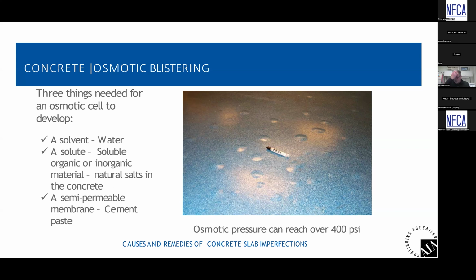And then what's done is it's reprofiled with a cementitious material that is suitable to be indefinitely damp. So you use a different cementitious material over the surface. It does not have the salts in it, and certainly wouldn't have a semi-permeable membrane. And then you put a moisture control material over top, patch and leveling, put flooring down, etc.